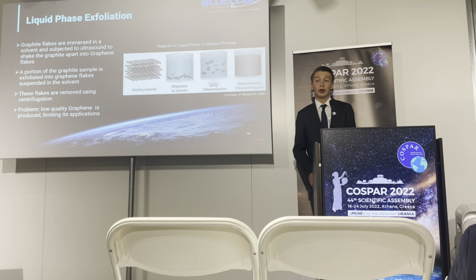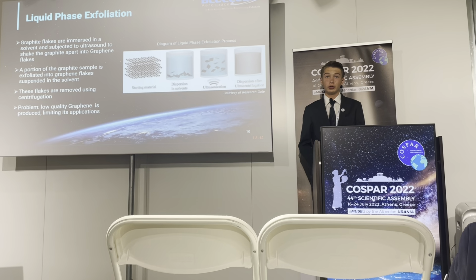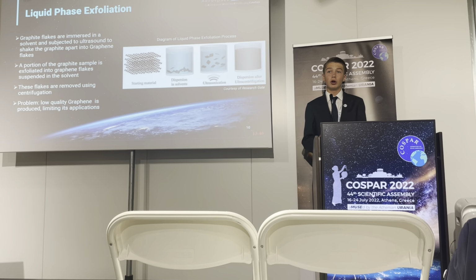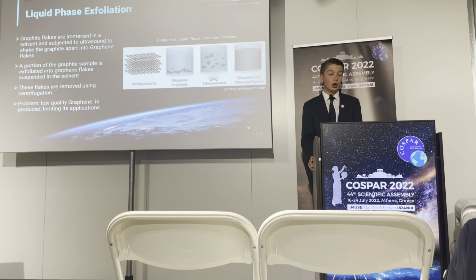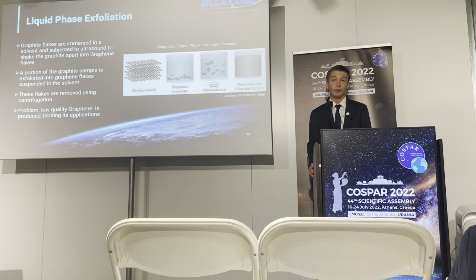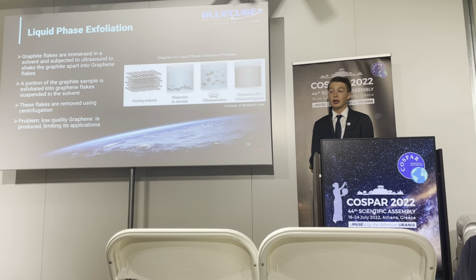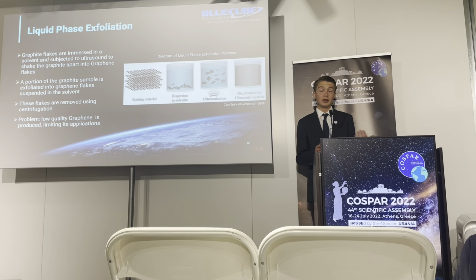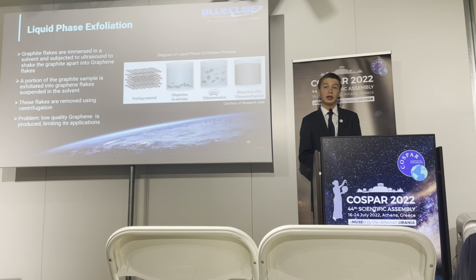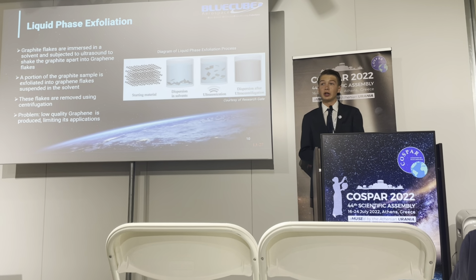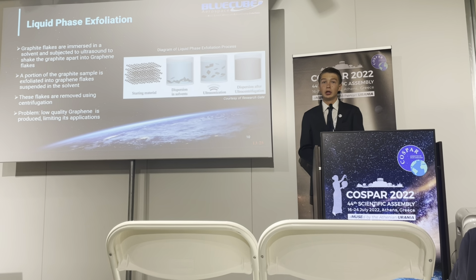There's some graphene flakes in the solvent, but the majority of it remains in the form of graphite, which is then removed using centrifugation. So even though this method is highly scalable, the main problem is that the graphene produced is of lower quality, which makes it harder to use in various applications and limits the benefits of this material.